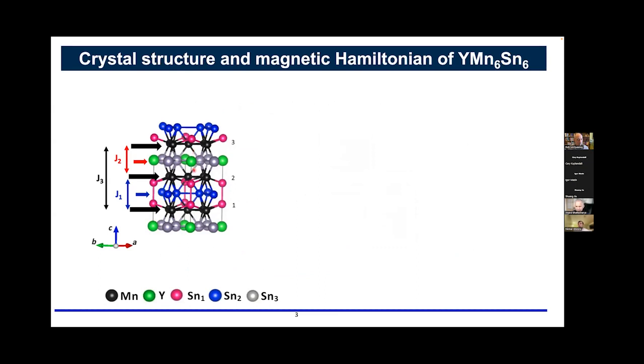plays an important role in the magnetic structure of these materials, especially because if we look between layer 2 and layer 1, it only contains the tin, and when we look between layer 2 and layer 3, there's a rare earth and tin containing layer. Because of that, the exchange interaction between layer 1 and 2 is different from the exchange interaction between layer 2 and 3. And if we include the next nearest neighbor exchange interaction J3, then there is an inbuilt frustration along the C-axis, and that drives a lot of different magnetic phenomena in this material.